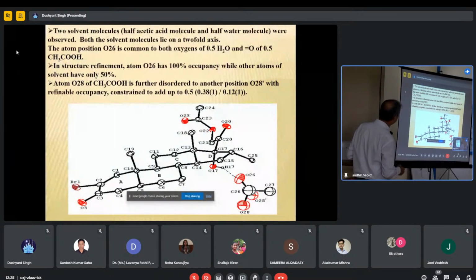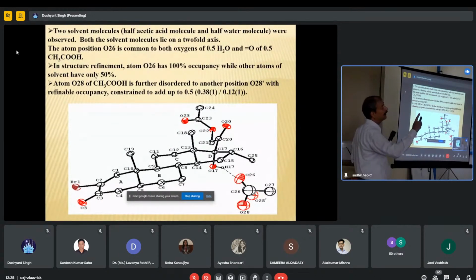Atom O28 of CH3COOH, acetic acid, is further disordered into another position, O28, with a refinable occupancy. Further, this oxygen was showing disorder. We have resolved it. In structure refinement, atom O26 has 100% occupancy while all other atoms do not. Unless you have knowledge of crystallography, no one can solve this kind of disorder, where one atom of a particular solvent is showing 100% occupancy and the other is showing 50% occupancy. Then you have to realize why it is coming so.